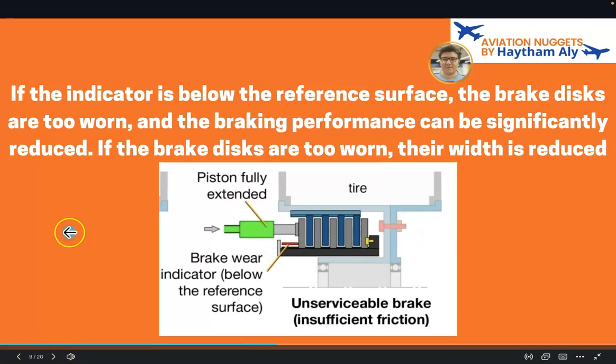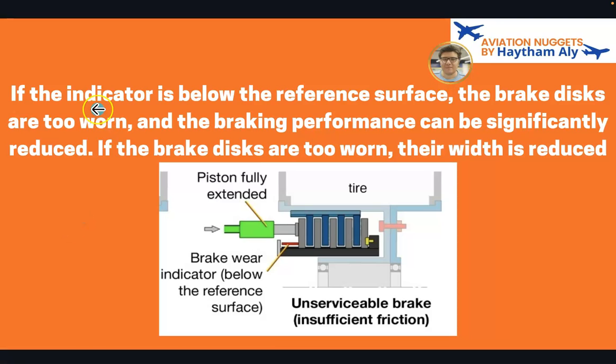Okay, everybody. So what we have just mentioned is written here now. If the indicator is below the reference, now you see the indicator is below the reference, so the brake discs are too worn now. You are now satisfied that the brake discs, rotor and stator width, is beyond the limit, okay, and the braking performance can be significantly reduced. Now this brake unit cannot satisfy a rejected takeoff scenario. So if the brake discs are too worn, their width is reduced. If the brake wear happens, the rotor and the stator that compose the brake unit now have less width, so their mass is less and their strength is less, so they cannot be ready to absorb the heat energy that will come due to